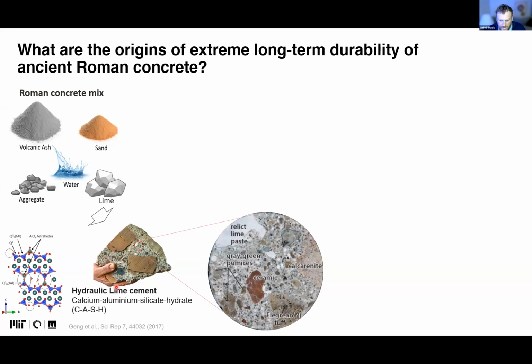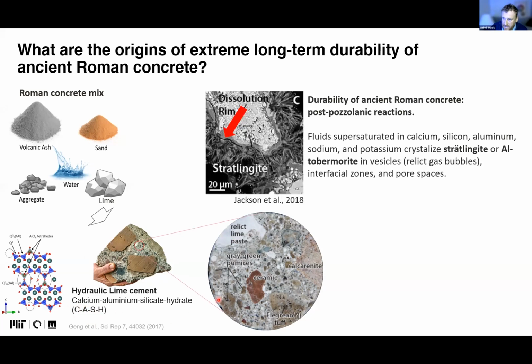Of course, hydraulic mortar means that we have this pozzolanic reaction that, because of the type of volcanic ash we use, gives us calcium aluminum silicate hydrates. Durability is of course of our interest, and it's very well studied by my colleague Marie Jackson. Marie demonstrated through several works that fluids supersaturated in calcium, silicon, aluminum, sodium, and potassium, after the pozzolanic reaction occurred, on the long time scale crystallize in some phases that basically fill the vesicles, relict gas bubbles, interfacial zones and pore space, so fill everything.